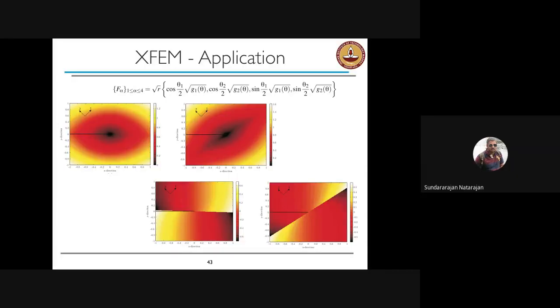Right. But to be able to use XFEM to do it, we had to come up with a new set of enrichment functions, because the isotropic enrichment functions that we were using for isotropic material were not able to capture the necessary physics, because they failed to have this information of the fibers in the model. So we had to come up with new functions. So these are the new functions where G of theta, or G1 of theta, G2 of theta, has the necessary information of the fiber orientation.